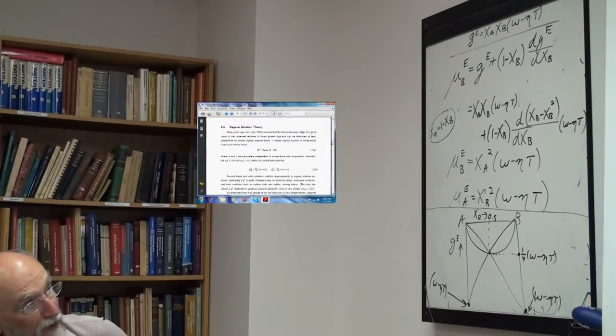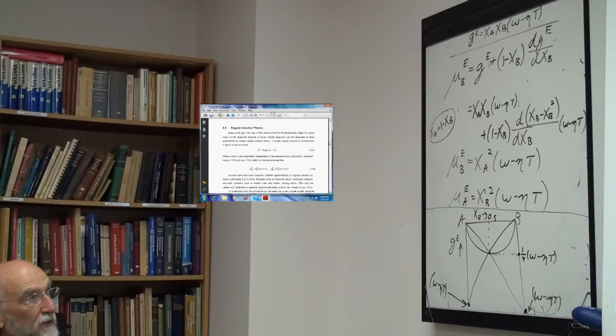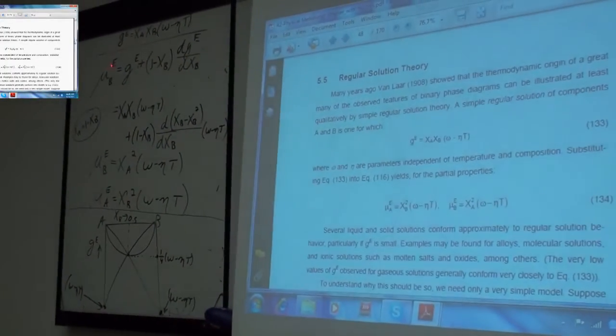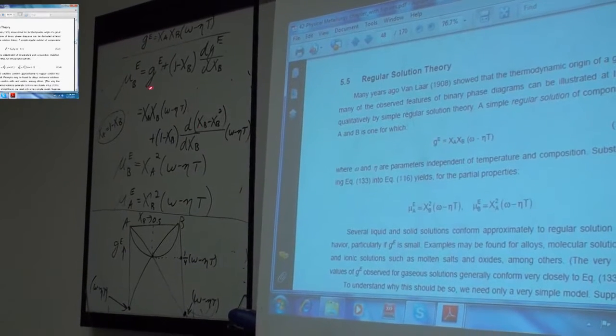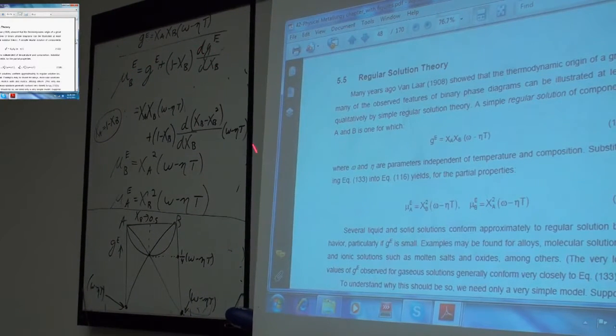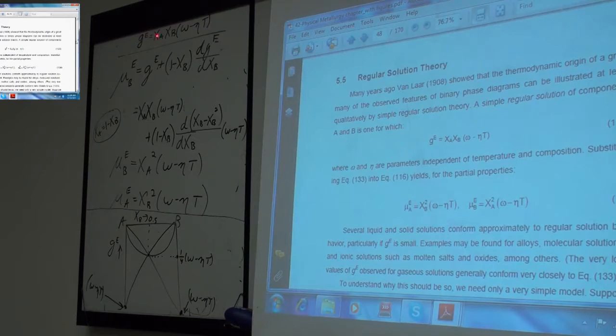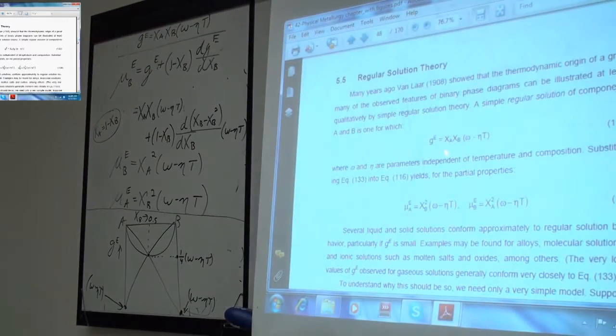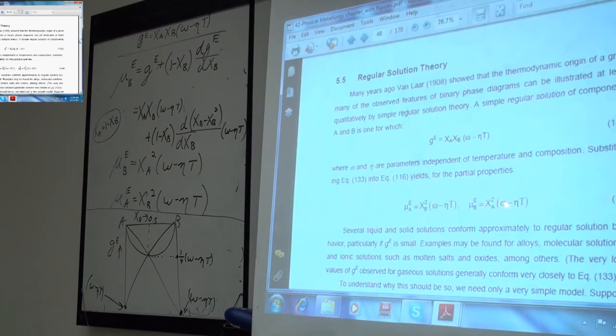Now, what are the partial excess properties, which will give us the activity coefficients? If you substitute this into equation 116, the common tangent equation, mu^XS of B is G^XS plus 1 minus X_B, and so on. If you substitute this equation for G^XS into the common tangent equation, which we talked about an hour ago, you will end up with these equations for the partial excess chemical potential. So mu^XS_A is X_B squared times the same constant, and mu^XS_B is X_A squared times the same constant. So these are also parabolas.